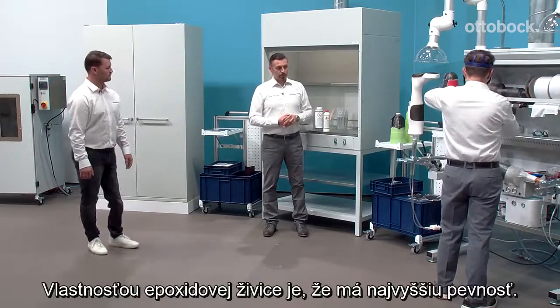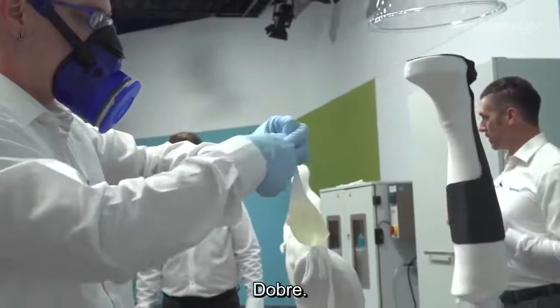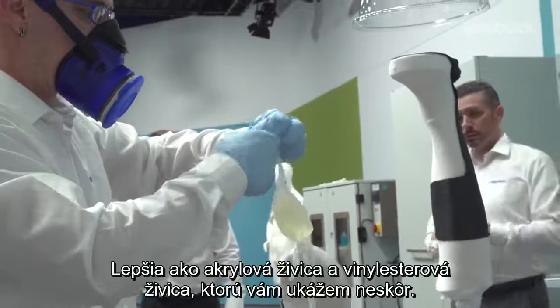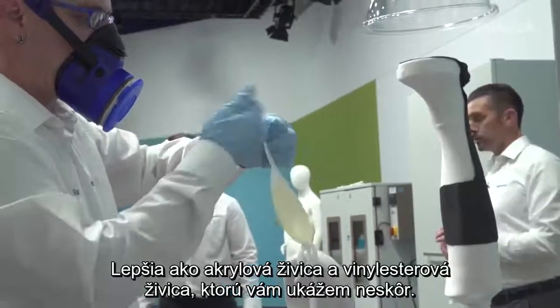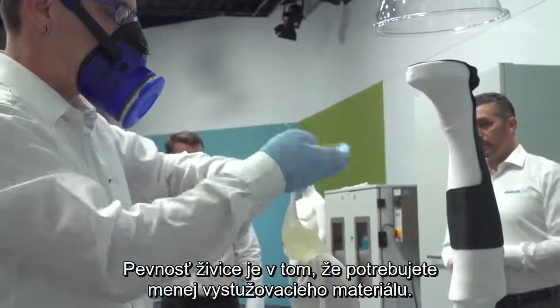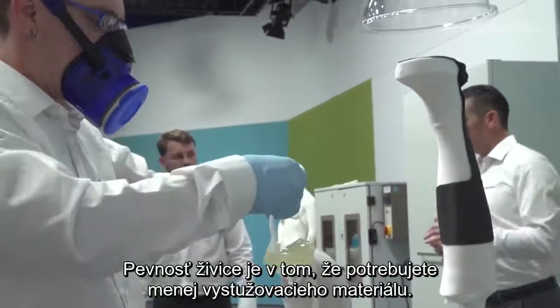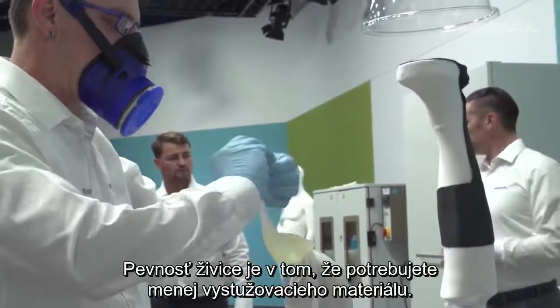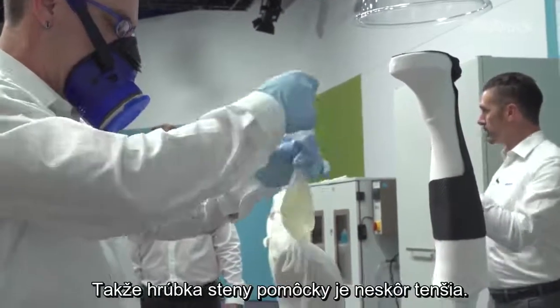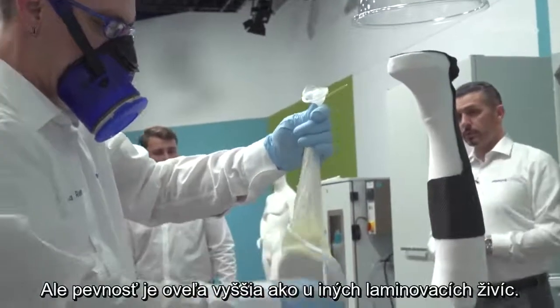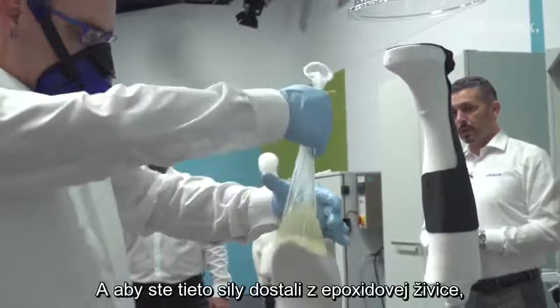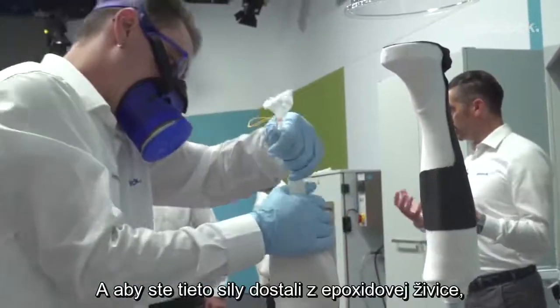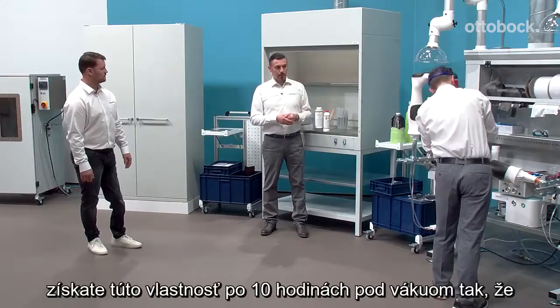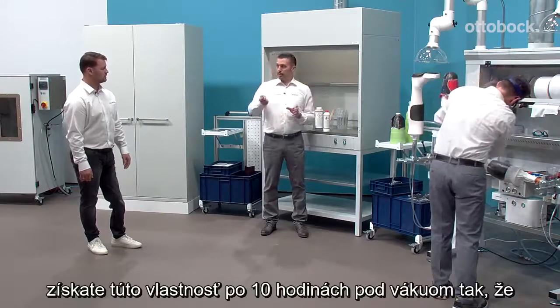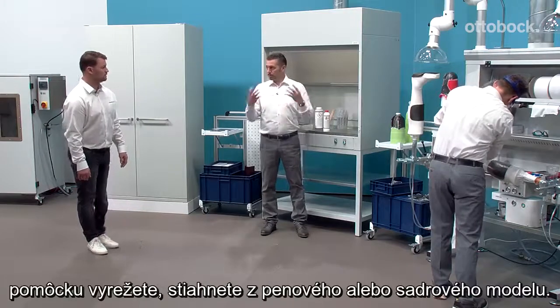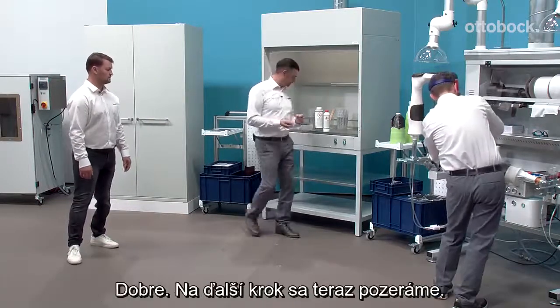So a property of the epoxy resin is it has the highest strength. Better than all the other resins, better than acrylic resin and vinyl ester resin, what I'd like to show you later. And because the strength of the resin is so high, you need less reinforcement material. So the wall thickness of the device later is thinner, but the strength is much higher than with other lamination resins. And to get this property, after the 10 hours under vacuum, you can cut out the device, remove it or demold it from your foam or your plaster cast.